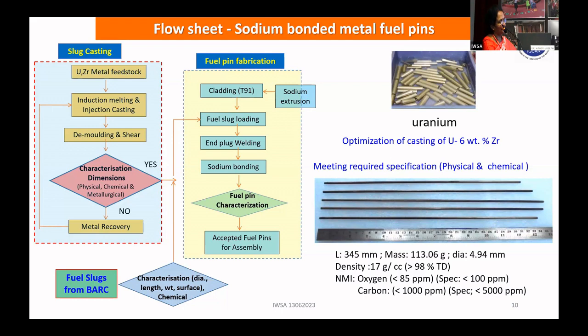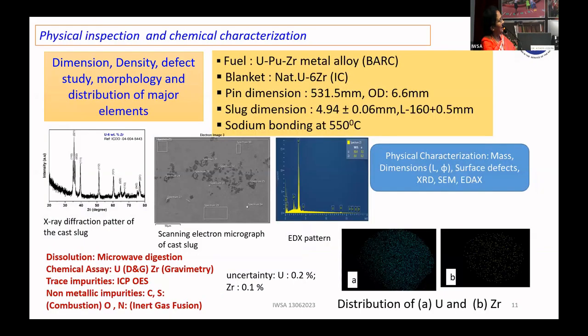And on the non-metallic impurities, oxygen should be less than 85 ppm, the actual spec is less than 100 ppm, and carbon needs to be less than 5000 ppm as per the specification, but what we get is less than 1000 ppm of carbon. And as I told you, we need to go for all the characterization: XRD to check whether it is U-6% Zr, metallurgical characterization, and the dimensions, the surface, everything is checked, mapping the distribution of uranium and zirconium to prove that it is uniform. In addition to that, we do chemical analysis of the material. The uncertainty in uranium is around 0.2%. The uncertainty in zirconium is around 0.1%.